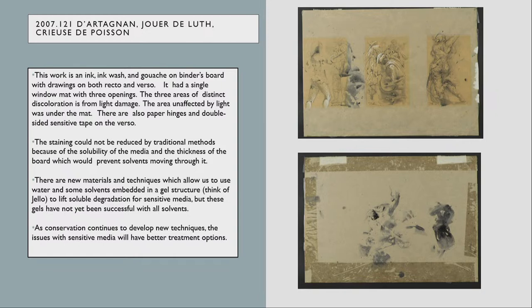But the issue here is that a water solution would not have helped, even if the pigments were not water soluble, because of the thickness. And if I put the whole cardboard into water, it would sort of start to unravel. Not necessarily, sometimes it can work, but it was a risk I was not willing to take.